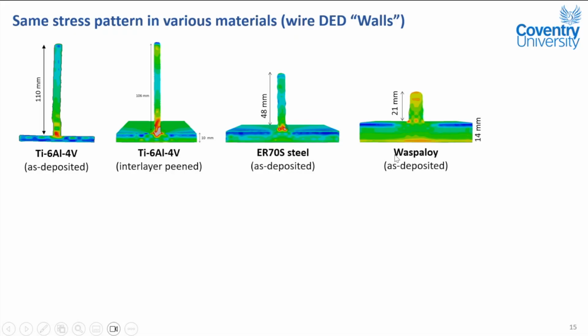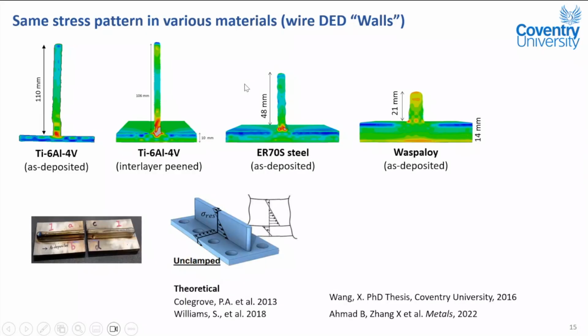Then we also measured the Waspaloy alloy. This is a new name. I think it's mainly nickel-based with some cobalt, but all of them show the red zone is at the intersection with the substrate. Then there's some compressive stress to balance it. So the measurement really agrees with the theoretical formula by Professor Williams and his colleague. There are two separate papers, quite well known.